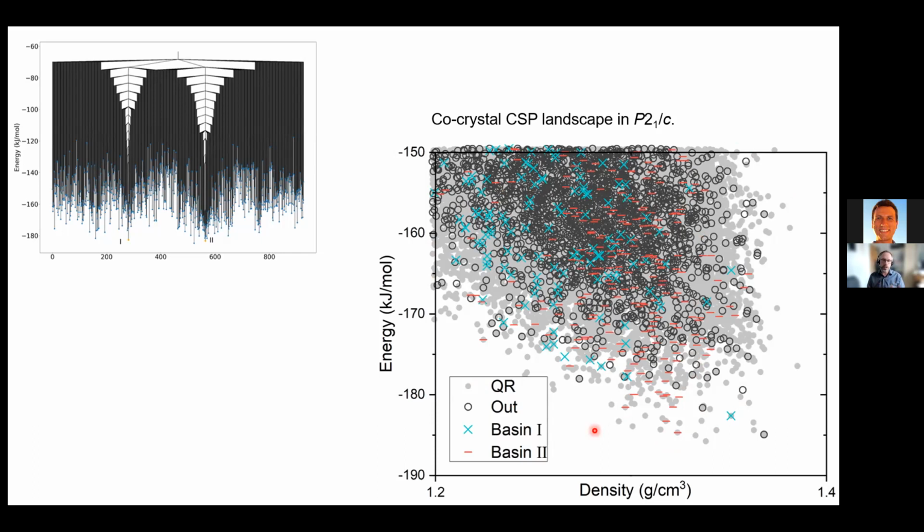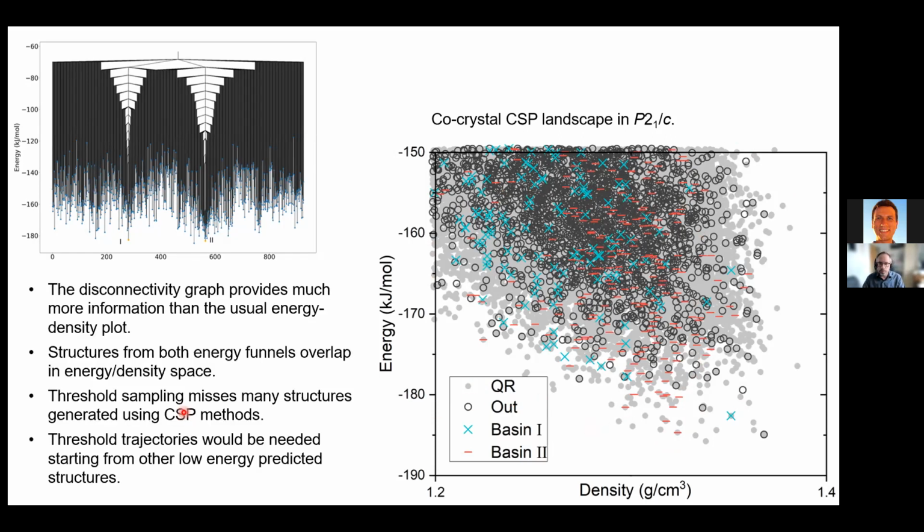and that can relate then to, say, the kinetics of transformation between these. In this case, these two polymorphs, although one is more stable than the other, can be sat for months on the bench and they won't transform between each other. Whereas if you had a lower energy barrier between them, then you might eventually get transition to the lower energy form.